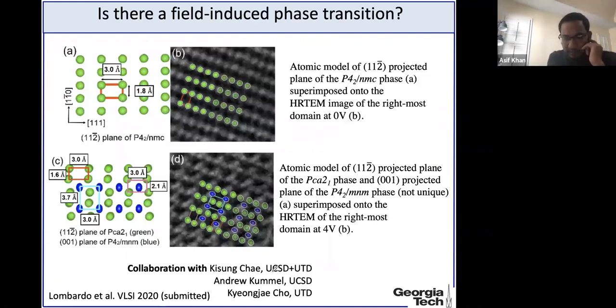Then we collaborated with our DFT colleagues who do DFT at UC San Diego and UT Dallas. Initially the 0 volt structure matches very well with the P4 2 NMC tetragonal phase. But when we go to 4 volts, the additional atoms do not really match any of the structures that we typically cite in our papers, for example, tetragonal P42NMC or PCA21 or PMN21. Our DFT colleagues found that it is somewhat of a match to an unusual, not often reported phase of P4 2 MNM.